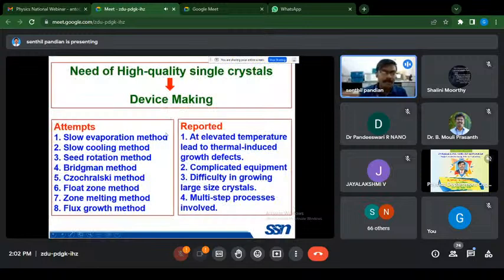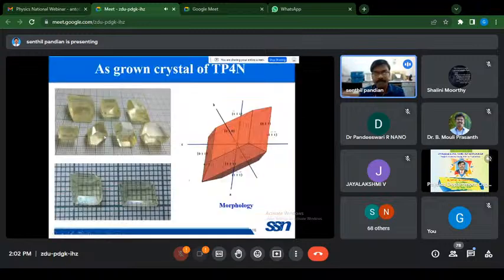So several attempts have been made to grow the crystals by this solution growth technique like slow evaporation method, slow cooling, seed rotation, Bridgman, Czochralski, float zone, zone melting, and flux growth method. But all the reported methods are at elevated temperature that leads to thermal induced growth defects, and it also has complicated equipment and difficulty in growing large size single crystals in these several methods, and multi-step processes are also involved.